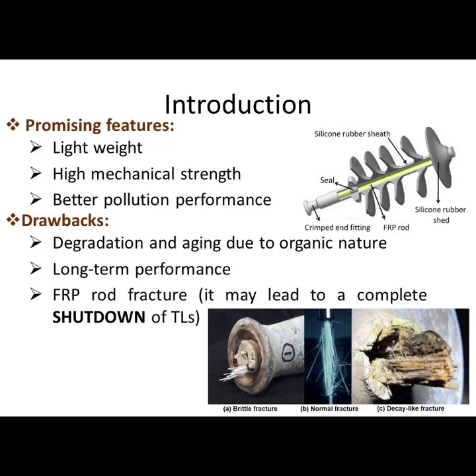However, these new insulators show some drawbacks, especially the long-term performance and reliability, degradation and aging under the action of the electrical discharges due to the organic nature, electric field enhancements near the end fittings, especially the high voltage end, and also FRP rod fracture, which may lead to a complete shutdown of the transmission line. There are two types of FRP rod fracture which are well known, which is the normal fracture due to the higher mechanical strength than the rated value, or the brittle fracture, which is due to the stress corrosion crack of the glass fiber.